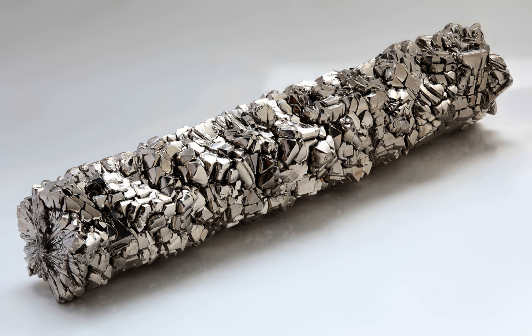Commercially pure flat product sheet plate can be formed readily, but processing must take into account the fact that the metal has a memory and tends to spring back. This is especially true of certain high-strength alloys. Titanium cannot be soldered without first pre-plating it in a metal that is solderable. The metal can be machined with the same equipment and the same processes as stainless steel.